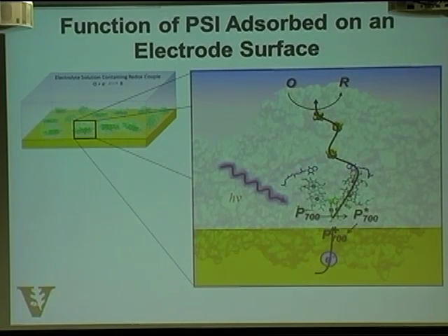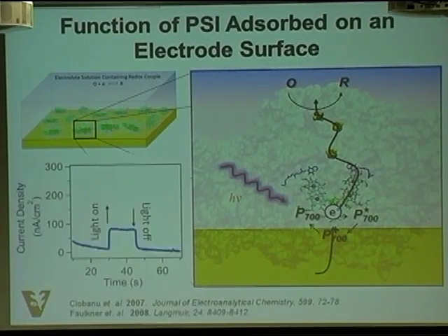And then we have to get an electron back into P700+ to reduce it back to P700. So basically, we're using a gold electrode here as plastocyanin to donate the electron into P700+. We are using a small molecule that can pick up electrons from the FB side of PS1 as ferredoxin does in the plant. Okay? So we're kind of making those two substitutions, and then ultimately trying to assemble these cells.